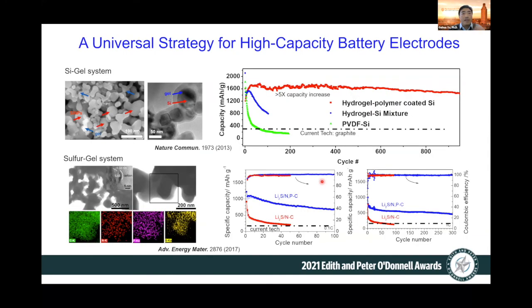And this framework is actually general for various high capacity, ultra high capacity electrodes. So for example, we also explored the gel with silicon. So you can see the different mixing methods yield very different results. If we go with conventional PVDF, a conventional binder, with silicon, it quickly decays due to the very big structural change of the silicon particle. If you just physically mix, it works better initially, but quickly decays. When you have these 2 levels of interconnectivity, they are very stable, and they have about 5 times capacity increase compared to the current graphite materials.